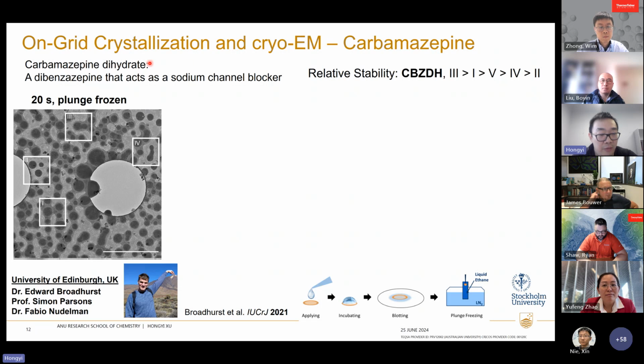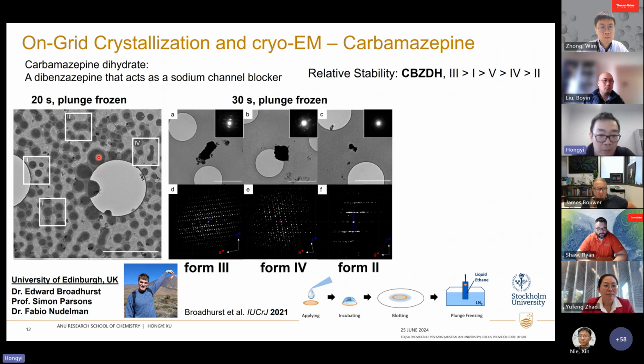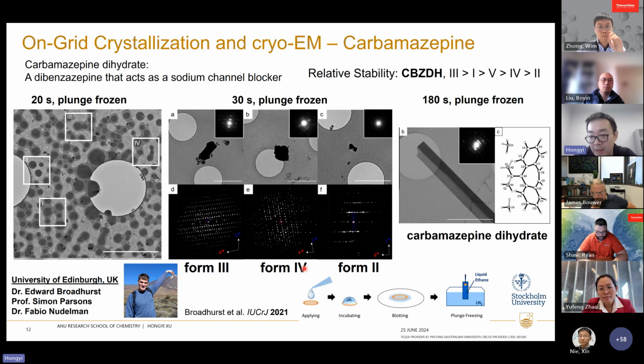This is carbamazepine. It's a very simple sample to work with. I think a lot of people use it as a test sample, but the most stable phase is the carbamazepine dihydrate, right? So after 20 seconds, we don't see any crystallization actually started, but after 30 seconds, when we plunge freeze, we actually see 3 intermediate phases that were not known to form during the crystallization process. And then at the end, if we wait long enough, finally the crystal becomes the dihydrate.